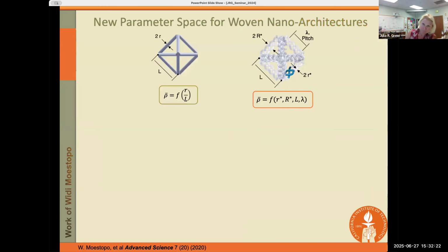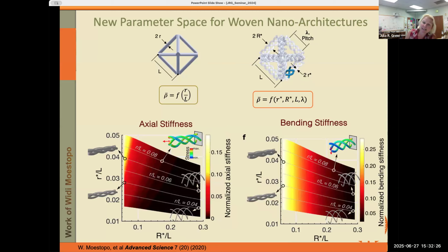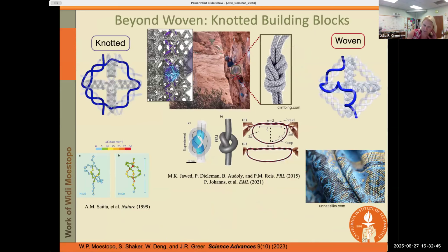Now, this is just to show you some of the modeling that shows us that what's really important here is the combination of the R over L, which is the slenderness ratio of each individual strand that's effectively braided together, and the overall thickness of each interwoven beam. And so now we can really control it. We control the stiffness, the bending stiffness, and the axial stiffness.